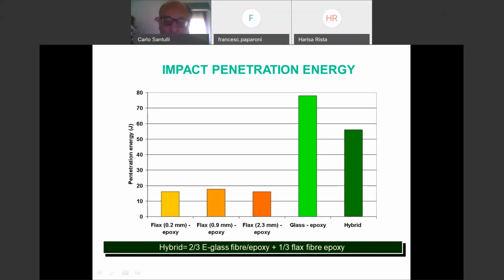So it was 2/3 and 1/3. I don't remember well, but it was 2/3, 1/3, and in practice, again, the effect was still reasonable. You could introduce 1/3. Possibly, if you introduce 2/3, then you drop almost to the level of flax epoxy. So, which might be a problem.